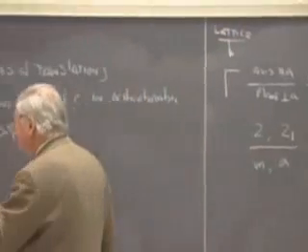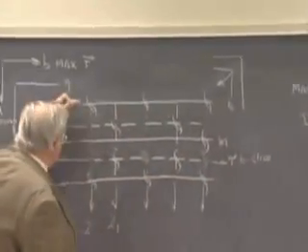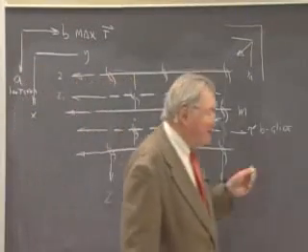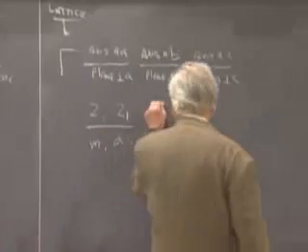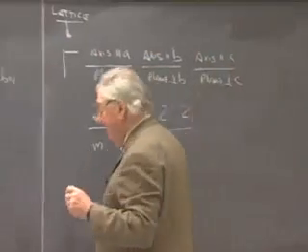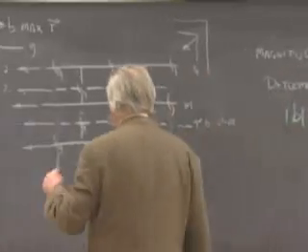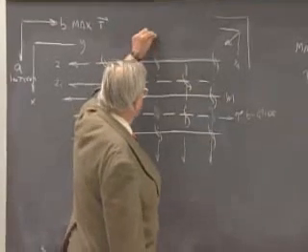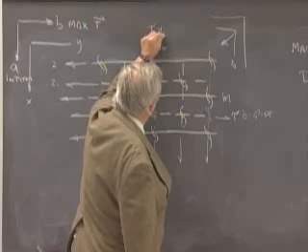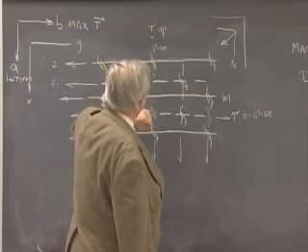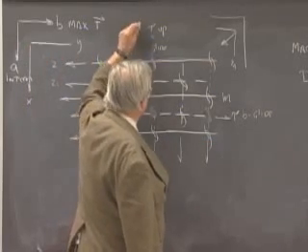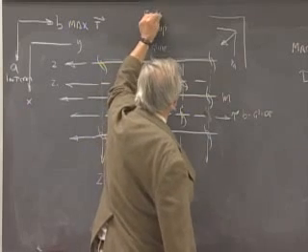I think you get the idea now, so let me move along quickly along the direction of B. Arrow for a two-fold axis, barb for 2 sub 1 screw axis. So again, there are two kinds of symmetry axes that could go in here for the axes that are parallel to B, either 2 or 2 sub 1. If we look at the planes that are perpendicular to B, there's a dotted line, and this is a glide for which tau is directed upwards. We're looking directly along the orientation of tau. The axis that is normal to the board is the C axis, so this is a C glide.